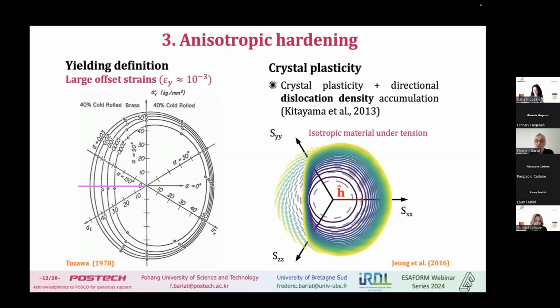This is just a linear strain path, okay? But to show that when we do a linear strain path, like pulling in this direction, and here it's uniaxial tension in this direction, the yield locus is given by the yellow contour here. And we see the same thing as before. We see a flattening of the yield surface in the direction opposite to loading. So it's something that we observe also in many works reported, that we get some flattening of the yield surface in the direction opposite to loading.